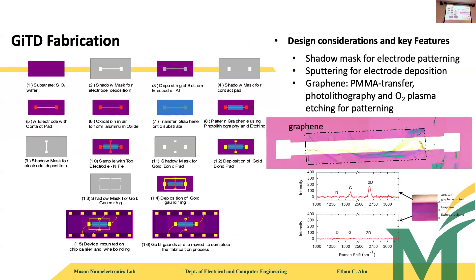The fabrication process has 16 multiple steps. I can transfer graphene nicely — using Raman spectroscopy to confirm graphene placement: no graphene peaks in regions without graphene, and clear graphene peaks where it was placed. This confirms graphene is precisely positioned in the area where tunneling occurs.